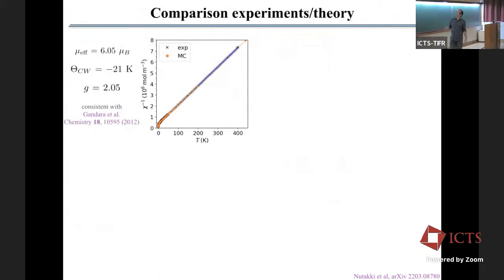And now we have studied this material experimentally. Okay. So here I'm going to show you the different experimental results and the comparison of these results with our theory. So first, the susceptibility, 1/chi as a function of temperature. So we have a nice long Curie-Weiss fit. So the Curie-Weiss temperature obtained is -20 Kelvin with a Landé factor of 2.05, which is consistent, and an effective magnetic moment of 6.05. All of this is consistent with a nice manganese 2+ magnetic ion.